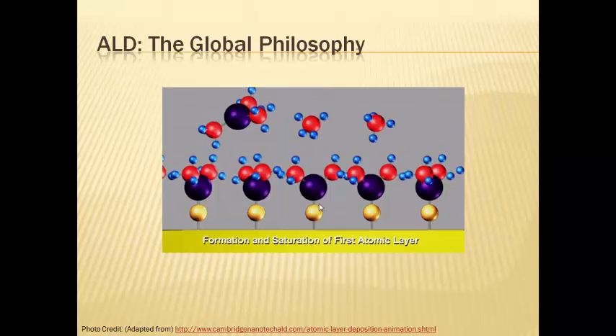Similar reactions continue to occur. However, it can be understood that if there are N hydroxyl ions for a certain surface in the presence of sufficient TMA molecules, N TMA molecules would react with them and form a bed of dimethyl aluminum oxide, and the reaction will stop thereafter. This is the self-limiting nature of the reaction which helps gain good control over layer-by-layer deposition with thickness precision to its monolayer.